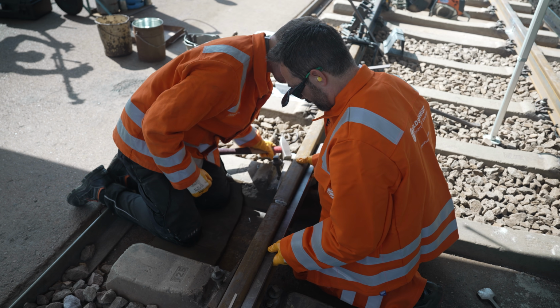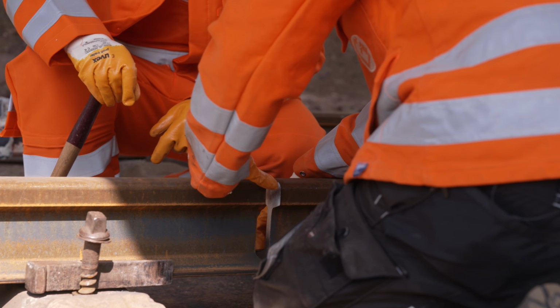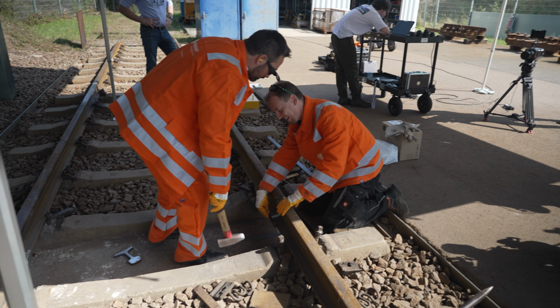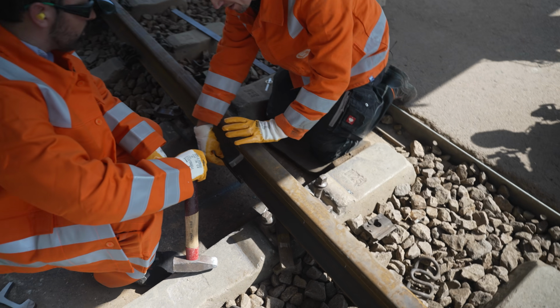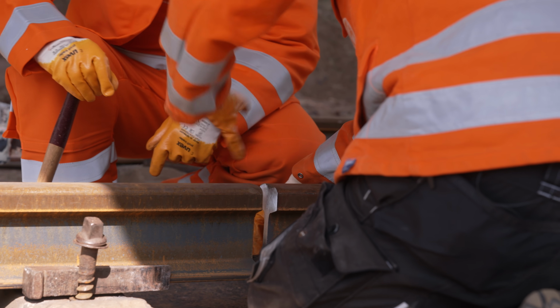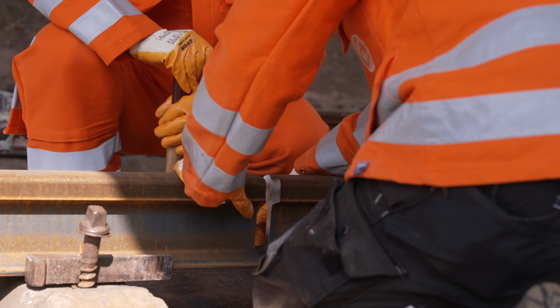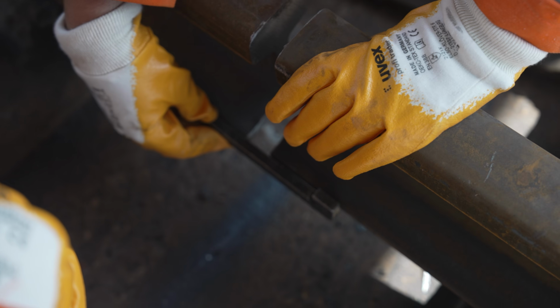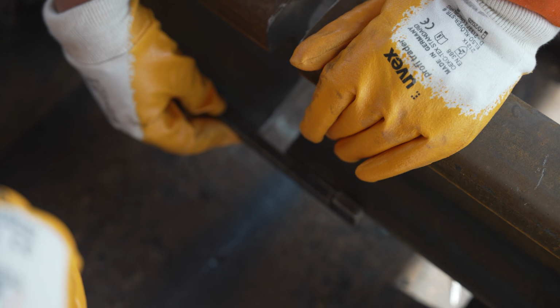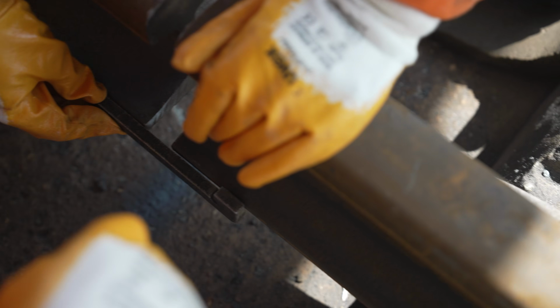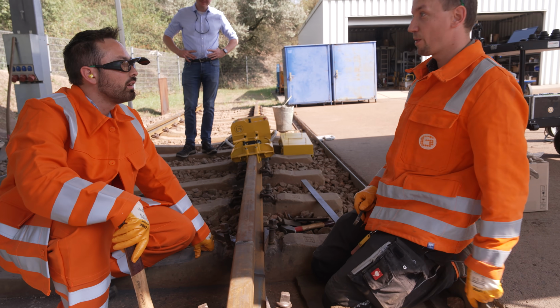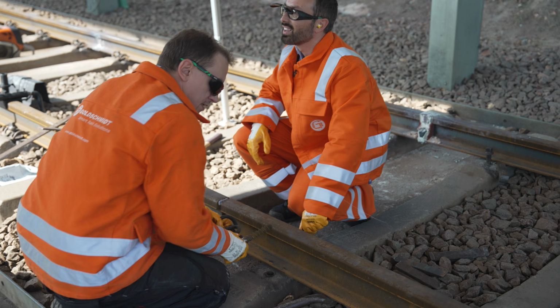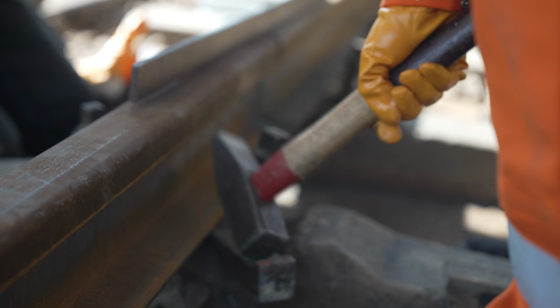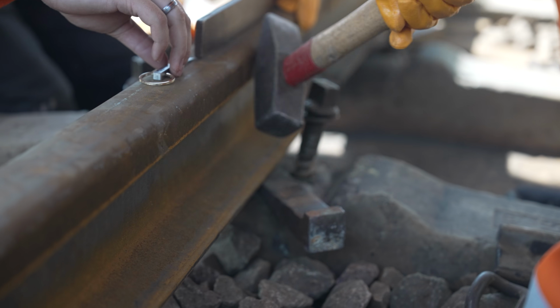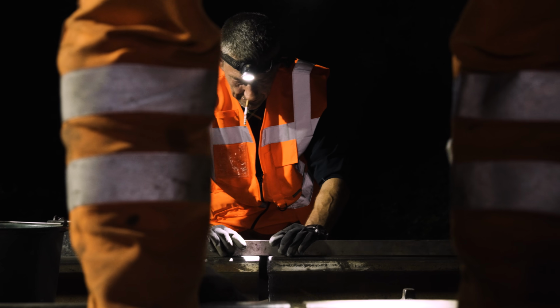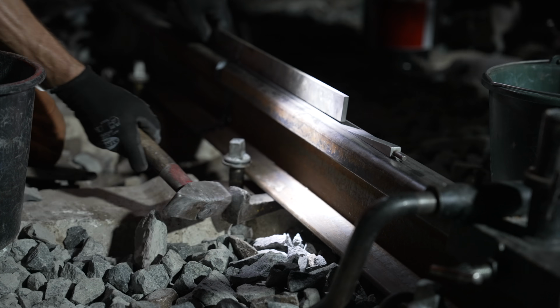When we were finally done with that, we double-checked the alignment at the head and foot of the rail, and we made a terrifying discovery. Our rail is twisted. Even though both rails were aligned at the top, one rail was slightly twisted relative to the other, which you can see by it not lining up at the foot. We have a maximum tolerance allowed here of 2 millimeters. Here we have more than 2 millimeters, so we have to untwist the rail. This, of course, threw out the vertical and horizontal alignment, so we had to do that all over again. Are we getting closer? A little bit more. But out in the field, the guys align the rail so quickly and easily, it really is an art.